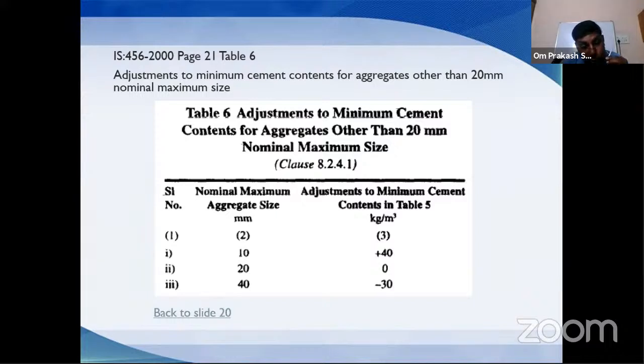And if we are using the maximum aggregate size of 40 mm, we can reduce the cement by 30 kg. And this addition and subtraction is with reference to 20 mm, where no adjustment is required. And why is it required? See, let's say we are using 1000 kg of aggregate in the concrete mixture. I am making 3 concrete mixes where I am using 1000 kg of coarse aggregate. In the first mix, I am using 10 mm only. In the second mix, 20 mm only. In the third mix, 40 mm.